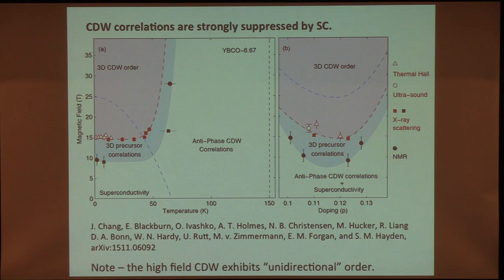How is the field applied relative to the planes? In the C direction, perpendicular to the copper oxide planes, to the conducting planes. Here's the phase diagram from this Johan Chang paper. Here's magnetic field, here's temperature. The data I showed you with the charge ordering peak growing and then shrinking was taken along a line along this cut. Here's a cut at the zero field superconducting TC, and what you see is that when you've suppressed superconductivity, the three-dimensional charge density wave ordering temperature coincides with what the superconducting TC was in zero field.